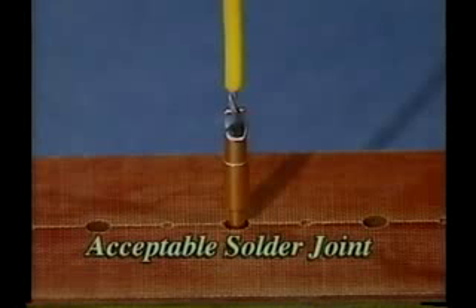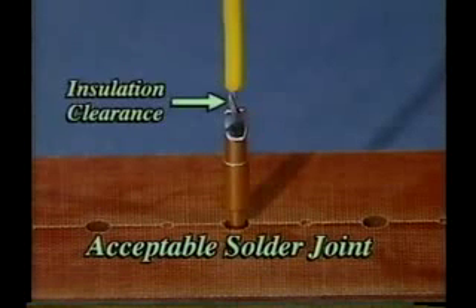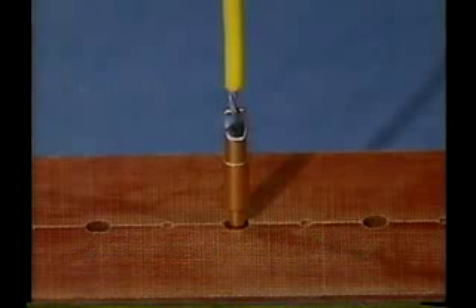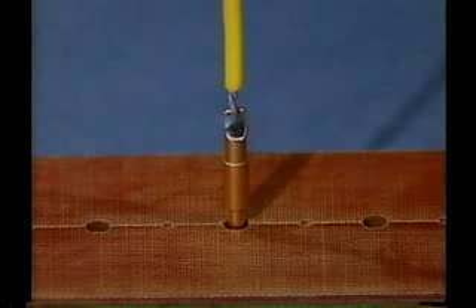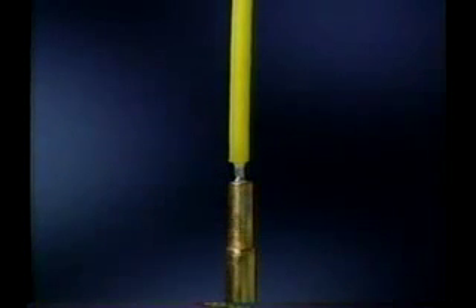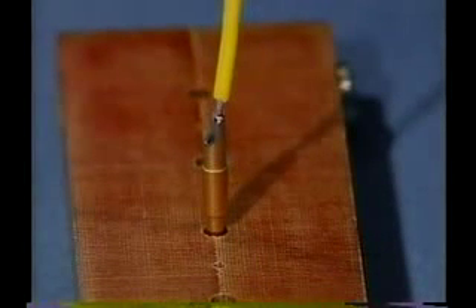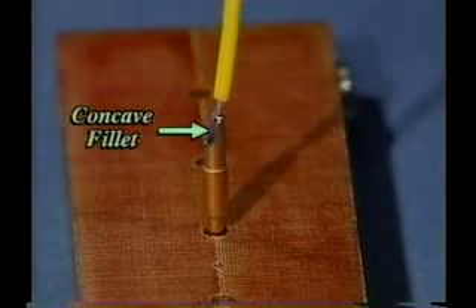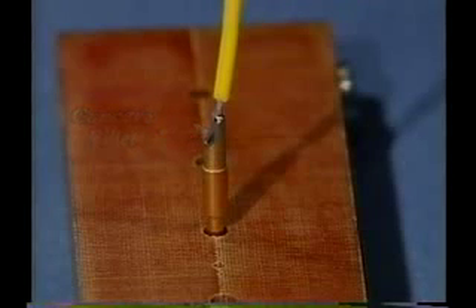Here is what the acceptable solder joint will look like. The wire is fully in the cup and there is an insulation clearance from the top of the cup to the insulation of the wire. The solder contains no pockets of flux or gas trapped within it and hasn't spilled over and down the sides of the cup. Also check that there is no buildup of solder on the cup where the soldering iron made contact. When the solder volume is correct, the fillets are slightly concave and show good wetting on all the surfaces.